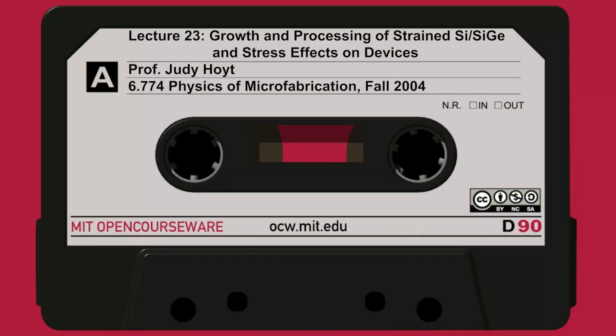How much smaller? Well, you can look on this curve. This is the difference between the band gap of the two as a function of germanium content. So here, if I have strained silicon germanium, you should use this upper curve, not the one that says unstrained. So at 20%, the band gap shrinks by about 150 millivolts, roughly. And you can read that right off the curve. Here at 50%, it's another number, maybe 350. So you have an idea of how it moves.